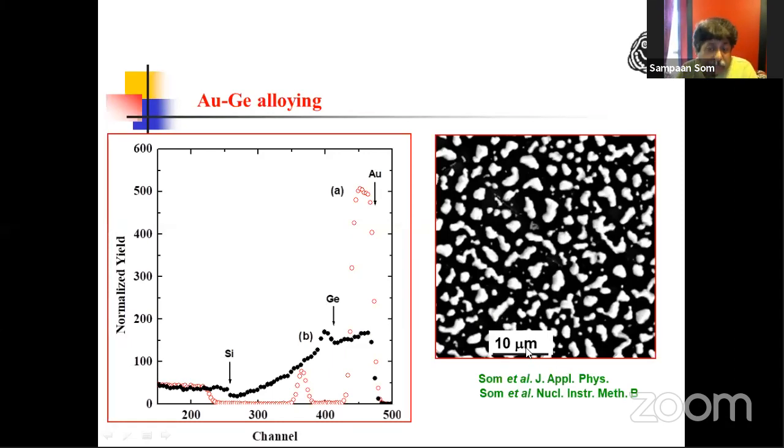And then after these formed, later on, after continuous bombardment as a cumulative effect, the dewetting also started taking place due to favorable surface and interface energies being available to these materials. So the continuous film first reacts due to ion bombardment, and under continuous ion bombardment, they start forming islands. So basically the continuous film breaks.